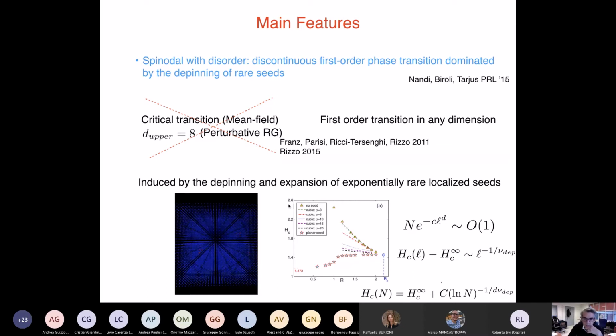What you have here is the critical value of the magnetic field as a function of the strength of the disorder. This line here is what we call no seed. We just take the system and study the hysteresis of the normal system. The other lines that you have here are lines in which we put a seed of the other phase by hand. Here the seed is of size 5, here size 3, here size 10, and so on and so forth. And what you see is that the critical value of the magnetic field at which you have the transition for this value of disorder decreases the larger the seed is.